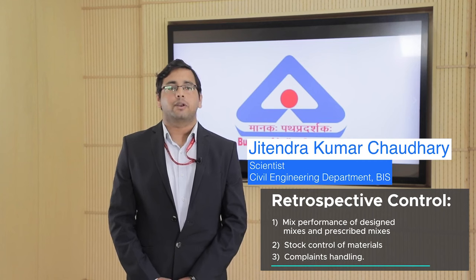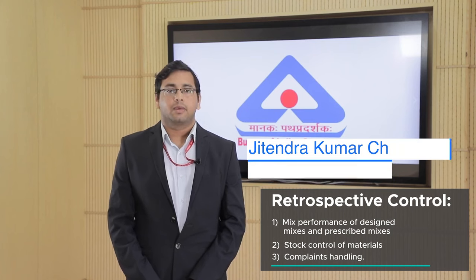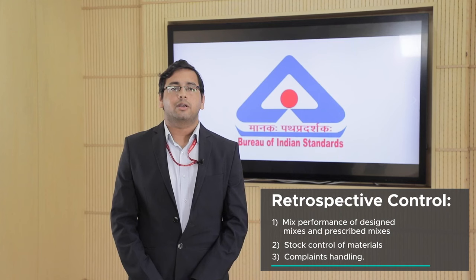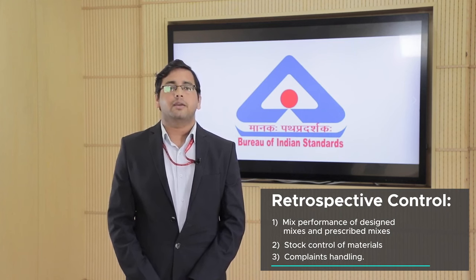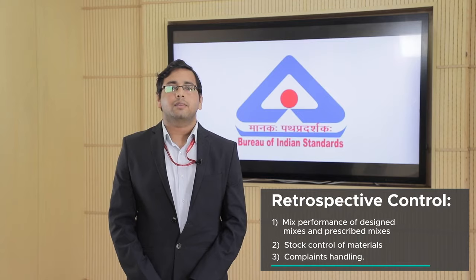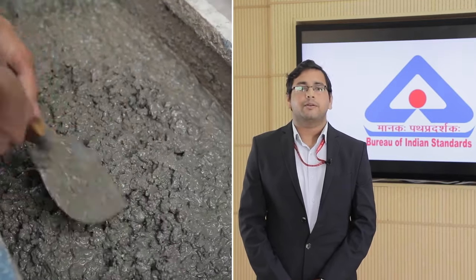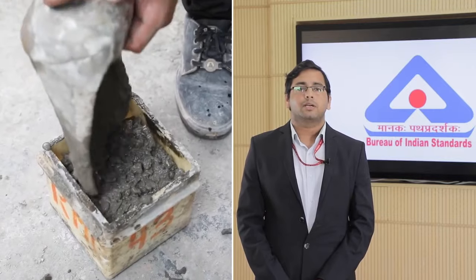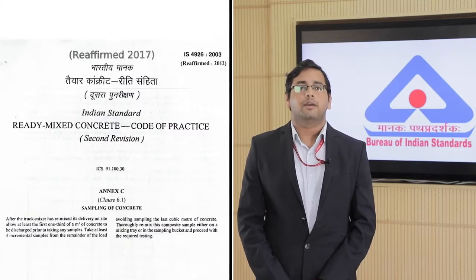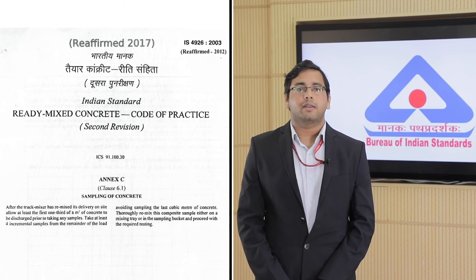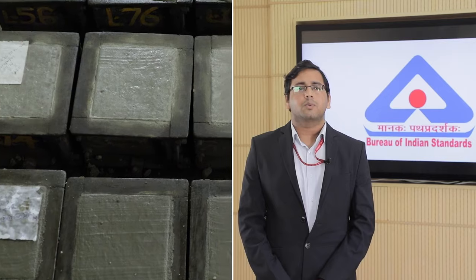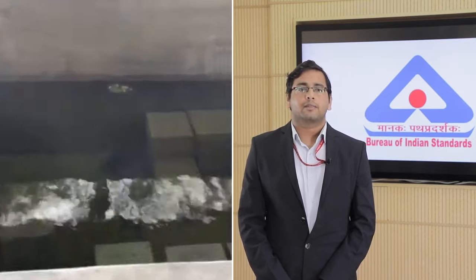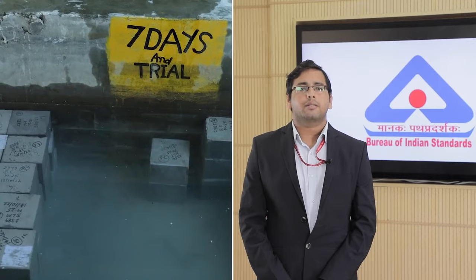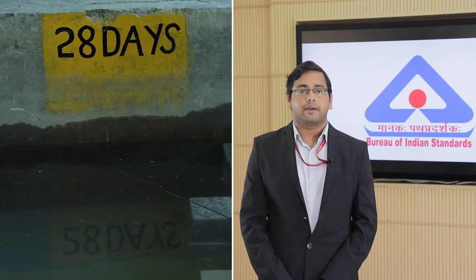The retrospective control involves testing of compressive strength of concrete cubes at 28 days and analysis of results to compare with the target values. Cube specimens are cast from supplied concrete as per frequency specified in IS 4926 for assuring the compliance of concrete strength. Sampling is done by trained technicians following proper procedures laid down in Annex C of IS 4926 and IS 1199 Part 1. After hardening, these cubes are demolded and placed in curing tanks under standard conditions for testing at 7 and 28 days as per prior agreement.